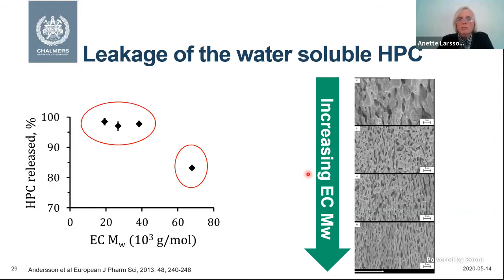And one way to characterize the porosity is to determine how much of the things that give rise to the pores you find has been released. And the amount of HPC release is determined here. And you can see for the three lowest molecular weights, you can get out about 95% of the HPC of the total amount you had in the beginning, but here you only get out 80%. This is due to that you have not so connected pores here, and it is also more difficult for the polymers to diffuse in more narrow polymer chains, so that takes more time, and therefore they can be locked into the coating. So we can say that the permeability has a very strong dependence on the porosity, but here